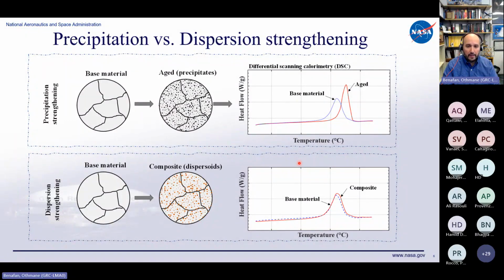A slight comparison in a cartoon way, precipitation versus dispersion. In the case of precipitation strengthening, you start with a base material with no precipitate. You heat treat it by aging heat treatments, and you promote precipitation. So what's the end result? As you precipitate, your transformation temperatures shift and your enthalpies and other properties change.